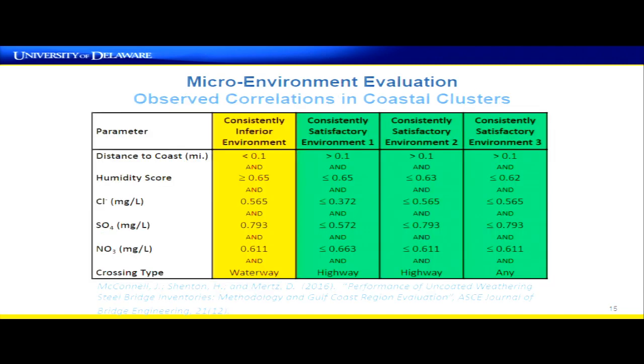So the conclusions of that for the coastal clusters are we were able to identify what we called a consistently inferior environment. So for a specific combination of distance to the coast, humidity, atmospheric salts, and crossing a waterway, the bridges in our study that had those criteria consistently had active corrosion. And then in contrast to that, we also identified several combinations of environments where, for any combination of those, all of the bridges had good performance. And there's a reference there if you want to read all of the details about that.